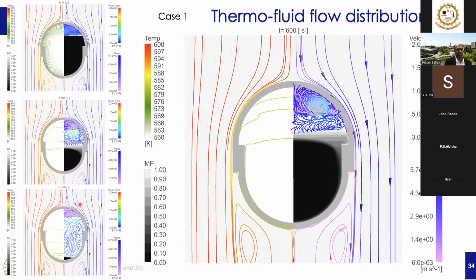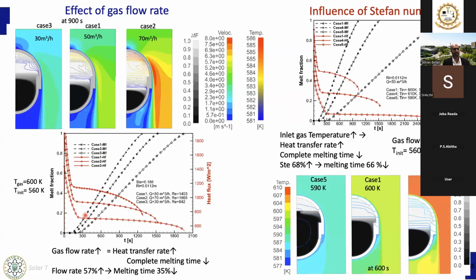In this slide, you can see what happens if we increase the gas flow rate, keeping other operating conditions constant, like capsule size, initial temperature, and fluid temperature. The only variation is the inlet gas flow rate from 30 to 70 cubic meters per hour. As you can see, when we increase the gas flow rate, the velocity obviously increases. Here you can notice that the melting rate is faster because the heat transfer rate is faster as well. And in this graph, you can see the melt fraction as a function of time, the black line profiles.